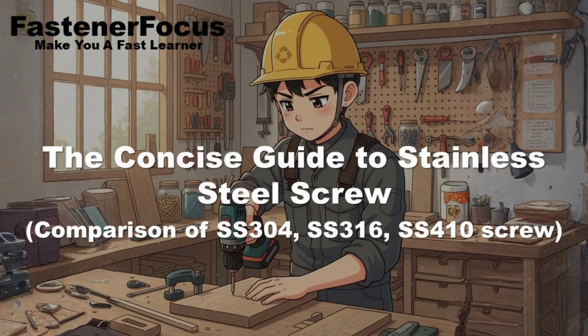And critically, how do they get their strength? Because this is a huge point of difference. It is. Crucially, they cannot be hardened by traditional heat treatment methods. You cannot just quench and temper a 304 screw. Their strength, which can range up to property classes like A2-80 or A4-100, is achieved entirely through work hardening, which is the tremendous force of cold deformation applied during the wire drawing and screw manufacturing process. This process distorts the crystal lattice, making the metal harder and stronger.